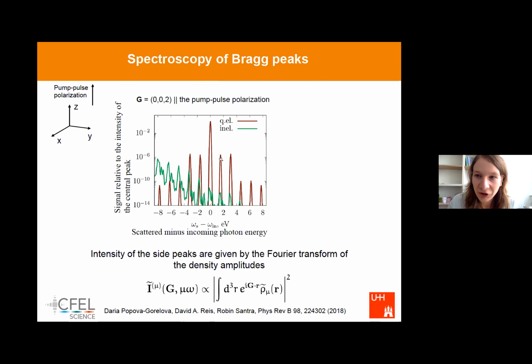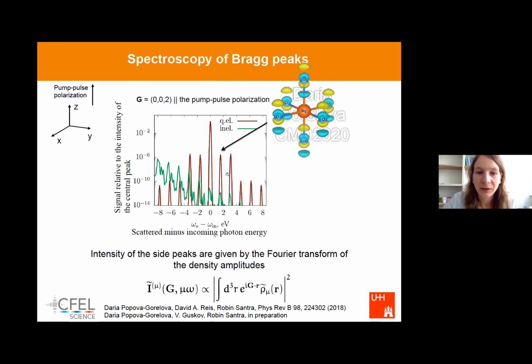So we could prove that each side peak is actually the Fourier transform of the corresponding charge distribution. So what do I mean by this? When a crystal interacts with this driving field, there is a first order charge distribution that would lead to the first order polarization, or you could say the first order harmonic, for example. And this charge distribution oscillates with a frequency omega. So within the Floquet formalism, we are able to calculate this, and it is shown here. You see it clearly shows the charge distribution as a dipole moment.